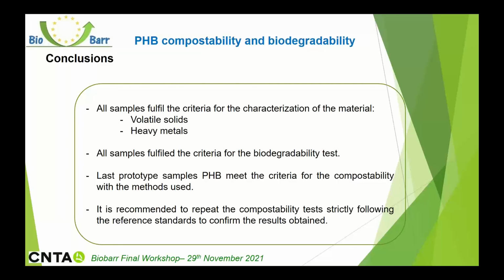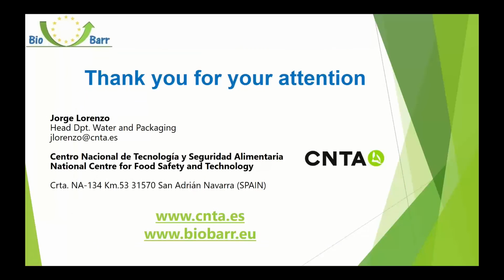But it's recommended to repeat the disintegration test strictly following the reference standard to ensure the result obtained, because with the modifications made, time and sample amount, we could not obtain a certificate of compostability. And this is all. Thank you very much for your attention.